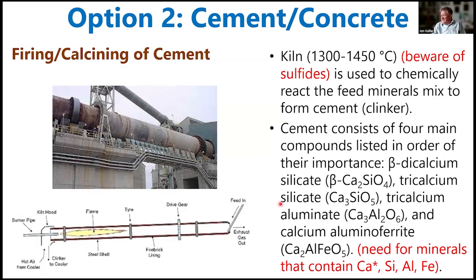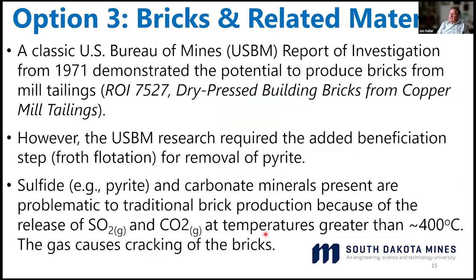And then I just list the chemicals that come from the cement process after it goes through the kiln and becomes clinker. So it's a series of calcium silicon complexes that make up this magical paste that we call Portland cement. But so there's a need for minerals that contain calcium. That's almost always limestone. And then these others containing silicon, aluminum, and iron that some tailings might fit the bill and could be part of either that cement making process or might act as a pozzolan during the actual formation with water. So that's option number 2.